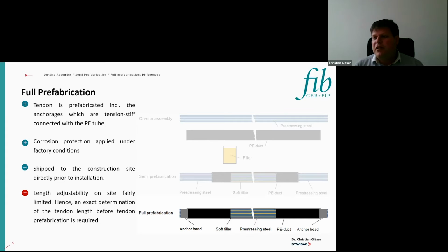Coming to full prefabrication, well, this means a prefabrication including the anchorages. In case of the external tendons, that's easy to do with having both anchorages installed, connected with the duct, and to even have this connection working during the stressing. This needs to be a tension stiff connection between the anchorage and the PE tube. So the advantage is, of course, corrosion protection can be applied under factory conditions, so standard processes, no weather influence, good quality control. The complete product is then shipped to the construction site more or less just in time or directly prior to the installation.